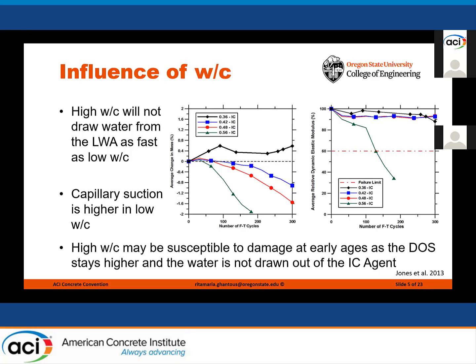And actually, in high water to cement ratio mixtures, the amount of water available is higher than the amount of water needed to replace the chemical shrinkage. This excess amount of water will then be unused and will keep the degree of saturation of the cementitious material higher than the critical value, and that will make the material more susceptible to freeze-thaw damage. That's why we can see that mixtures with high water to cement ratio did fail freezing and thawing cycles.